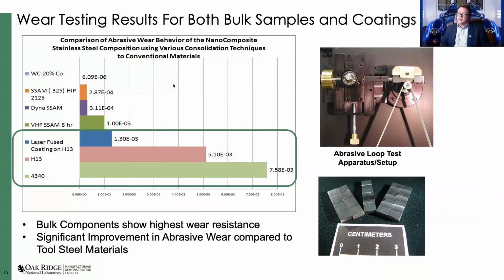We then started doing some abrasive wear tests. This is just an example of this, where you start showing drastic decreases, about a 5 times decrease in what we were seeing for abrasive wear, as you can see, comparing the laser fuse coating on H13 versus what you would see for H13 by itself. Obviously, in this scenario, the smaller the bar is, the better. You can also start to see the comparisons with the tungsten carbide cobalt as we were looking at fully dense material. Hence why I really think the sweet spot is how you use these as materials to surface some of the steels we're looking at.